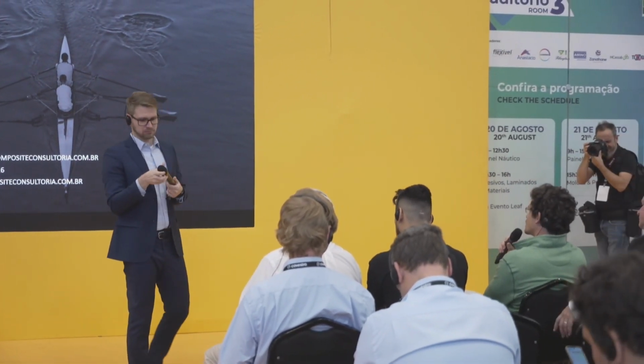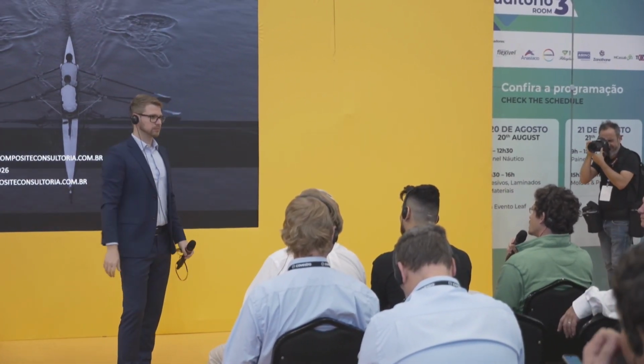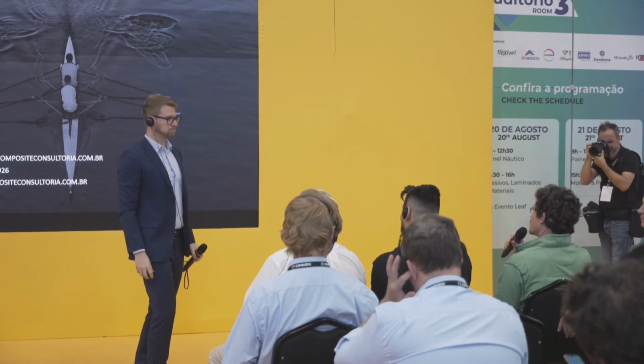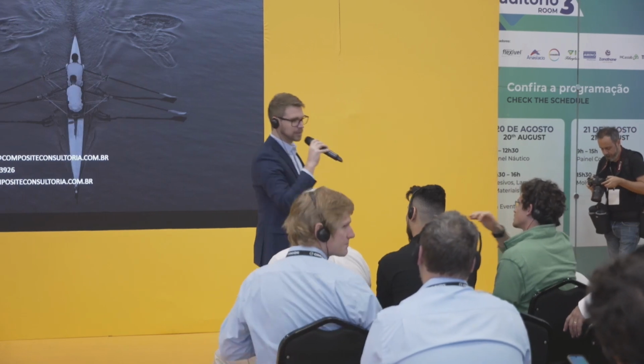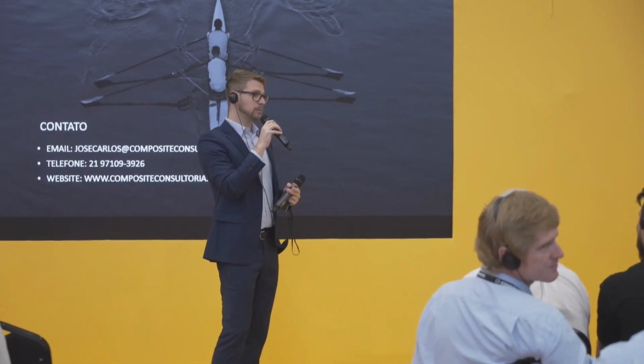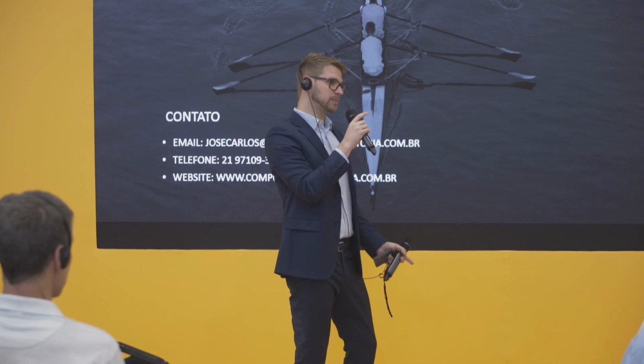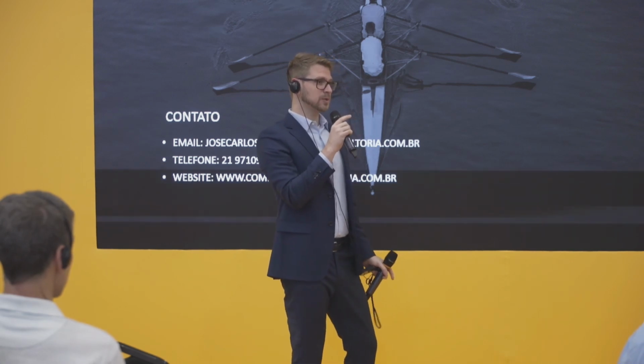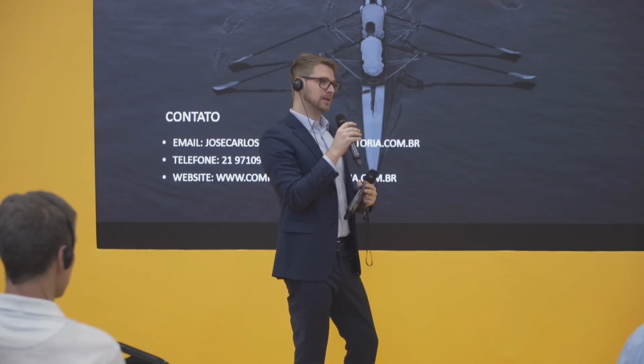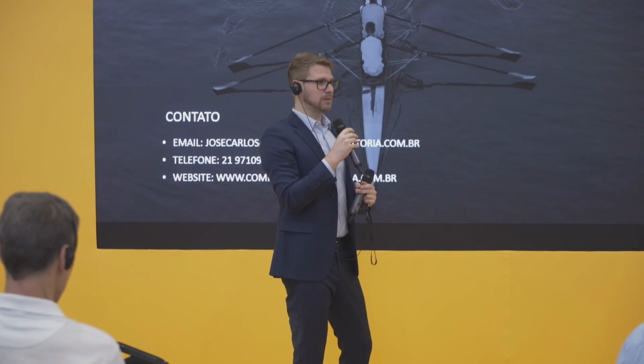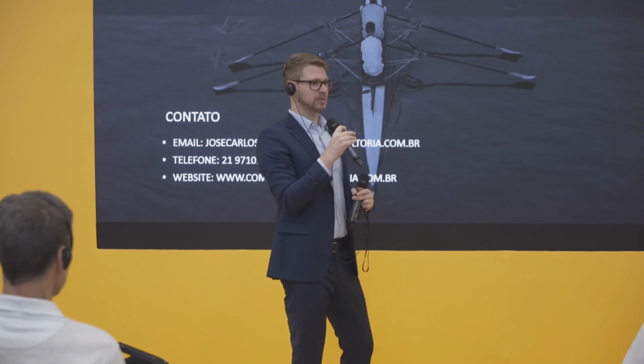And about using epoxy resin in these hulls, do you think that will reduce the weight of the vessel? No, not the weight. The density, the resins are very similar in their densities. We don't have such a major difference between, for example, the density of an epoxy versus a vinyl ester for the overall weight. What we do know is that it will last longer if there's a greater adherence between layers. In terms of weight, though, I don't think that there's a significant difference. The density is so similar, that's what it is.